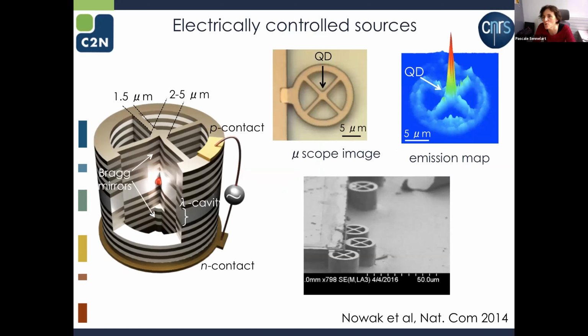To do that, we had to modify our technology. It's no longer the simple pillars that I was presenting before. We need to make an electrical contact. So we don't etch all around anymore. We make this kind of structure where we have 1D ridges that connect the cavity to a bigger frame. It doesn't change so much the optical confinement, but it allows us to apply an electric field on the device. And we still use the technique that I was presenting before. We still put the quantum dot exactly at the center of the structure, but now we can write anything we want around the quantum dot.